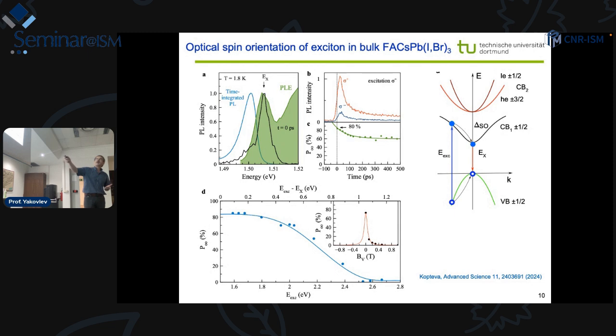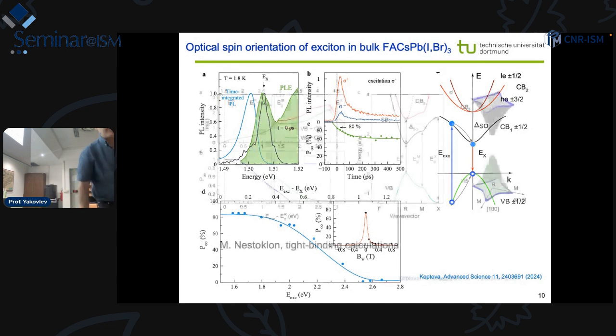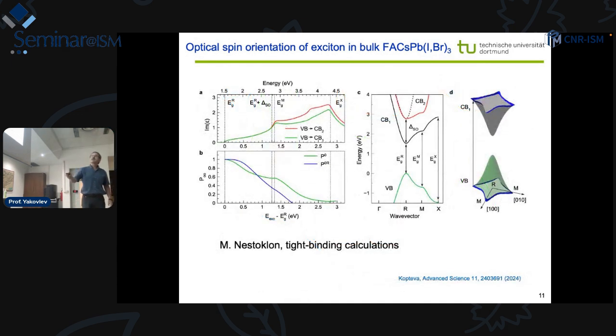When we go to the larger k vectors, where it mixes with another band, the generation mechanisms are not so pure. And then we come to Misha Nestoklon, and he calculated this. So this is the band structure, counted for R minima and M minima. And he really calculated that when we go up, some detuning of about 1 electron volt becomes detrimental for the generation efficiency. So actually, we may conclude that the effect of this decay, what we observe, is fully aligned